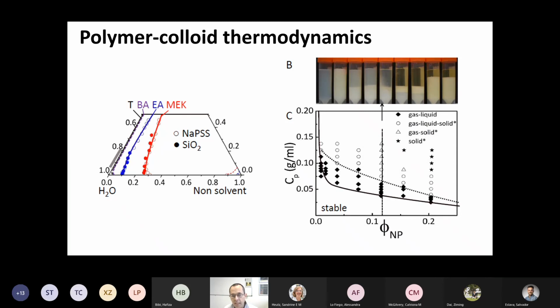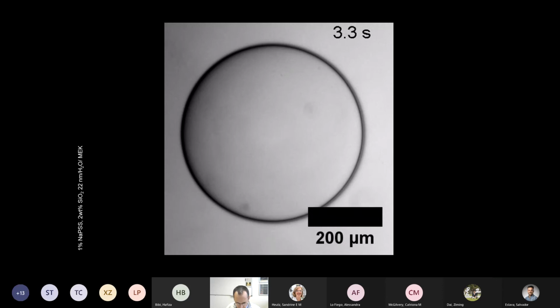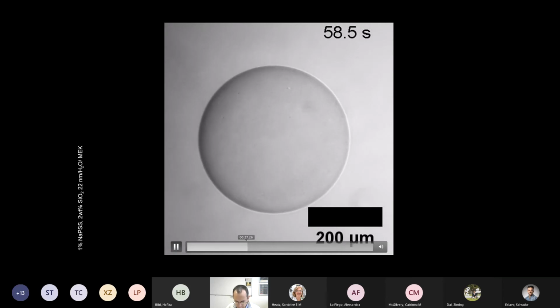But now let me pick something that interacts. So the same silica particles with the polymer. This is the kind of graph that people in colloidal physical chemistry plot. So this is the concentration of the polymer against the concentration of the nanoparticles. And we come from what's called the gas state, where they are miscible, and we cross into the liquid state where they now demix. And that corresponds to these structures over here, where you can see a stratification. I'm going to select the demixing process that is spinodal, and we'll see what happens here.